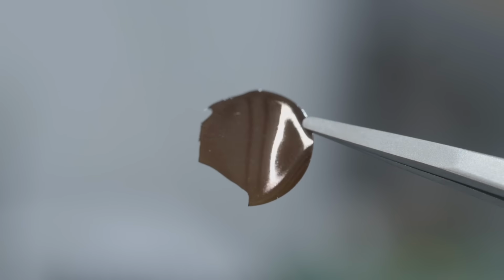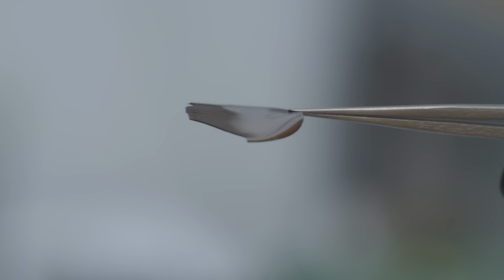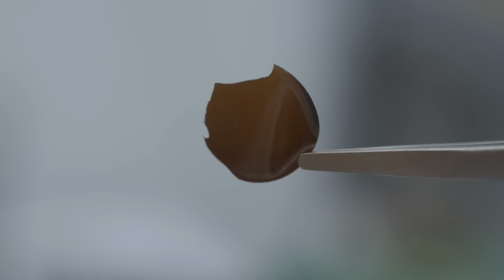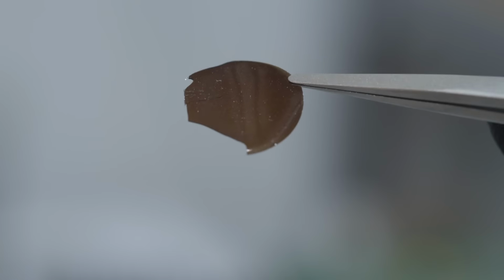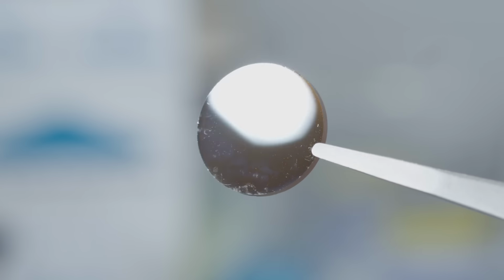To resolve this, I decided to tackle it in two ways. First, we can just use a different substrate that isn't a semiconductor, like glass. It makes the electron beam lithography step a little more complicated, but it entirely rules out any kind of interference from the substrate. Honestly, I should have just done this right from the beginning, but, hindsight and all that. So I tried using glass cover slips at first, but the furnace temperature is just hot enough that it makes the glass start to slump. So I had to switch to using fused silica, or quartz.